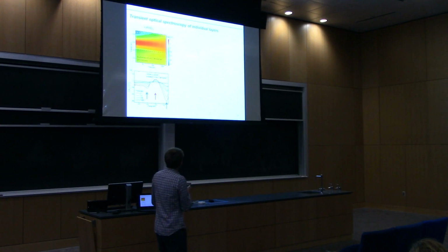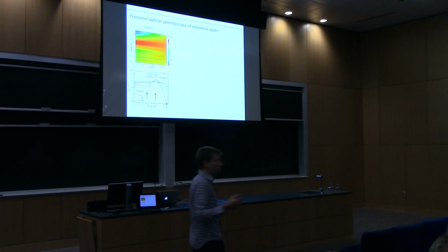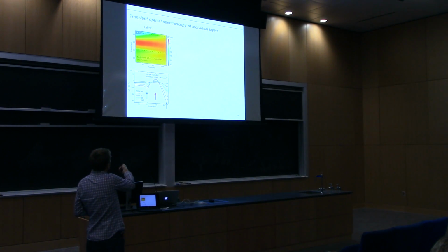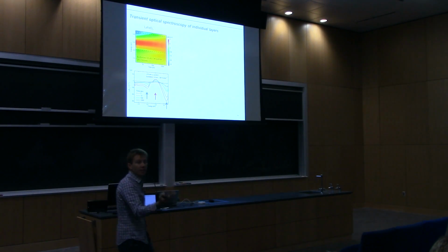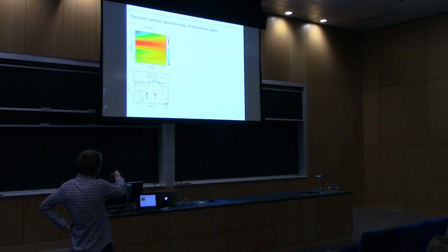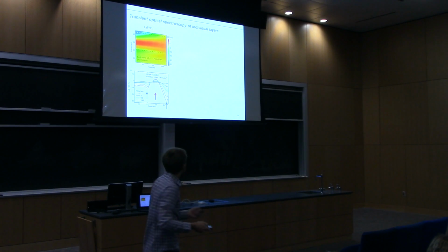All right, here's what the transient absorption spectra look like. This is all just measured at room temperature. This is lanthanum ferrite excited at 4 eV, so above the gap. And this is just a plain film of LFO, so this is a control. What you see is that there are 2 negative transients that occur right around those optical transitions. We also have a positive feature here around 3 eV. And then here's the time dependence of them. You excite, they last, and then they decay over time.